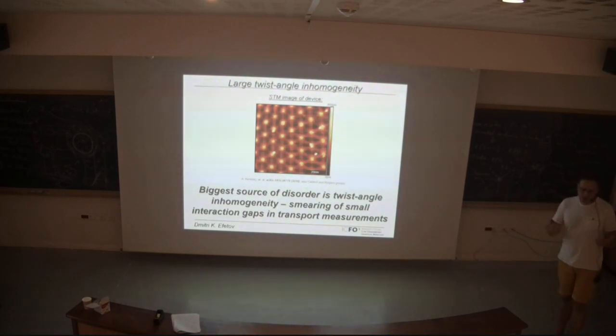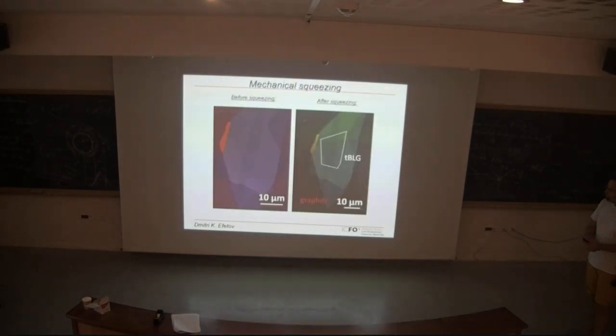And basically we think that a lot of the systems are very strained, and strain adiabatically evolves across the system. What strain does is it changes the periodicity of the moire lattice very adiabatically and periodically. Of course, if this region would be a magic angle, this would be something entirely different, and then here we wouldn't expect, for example, superconductivity to arise. So this is also where this phase separation for the Josephson junctions arises. Okay, and what we did in my group is we tried to really improve this strain relaxation within the van der Waals stack.